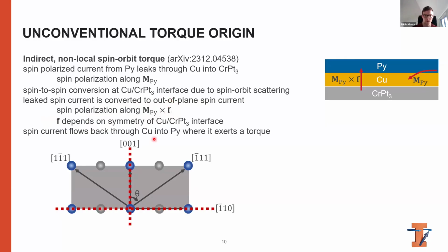So how does this work? We have two mirror symmetries in the chromium platinum 3 crystal structure, and this is independent of whether we have ordered or disordered chromium platinum 3. One is along the 001, which was the 0 degree case, and one is along the 1 bar 10, which was the 90 degree case.